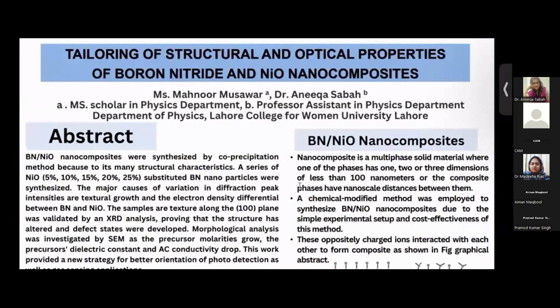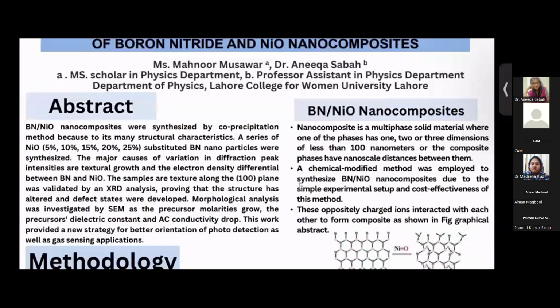The abstract of my research: boron nitride nickel oxide nanocomposites were synthesized by the co-precipitation method. A series of nickel oxide at various concentrations in boron nitride nanoparticles were synthesized. The samples textured along the 100 plane were validated by XRD analysis, proving that the structure has altered and defects were derived in the boron nitride nickel oxide nanocomposite.